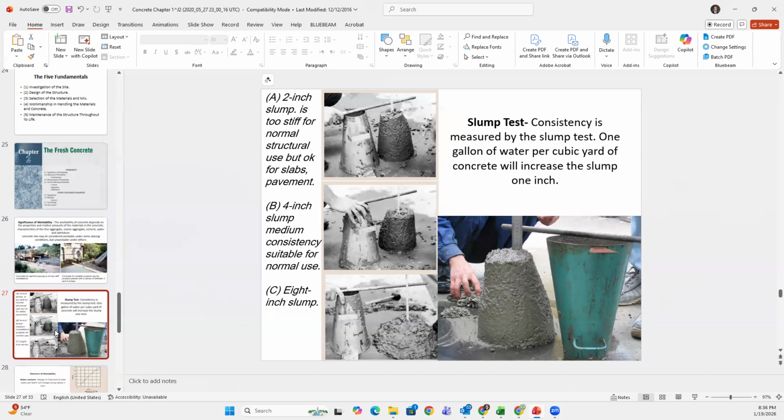In other words, concrete will slough off. As soon as you dump the cone backwards, first you feel it has closed at the bottom, so the container becomes full of concrete. Then you rod it a few times to make sure it's the right mix, and then you lift it, you dump it slowly. When you dump it, any fresh concrete will slough off, but that sloughing should not be more than 4 inch. If that's what you get, the job passes the concrete slump test.